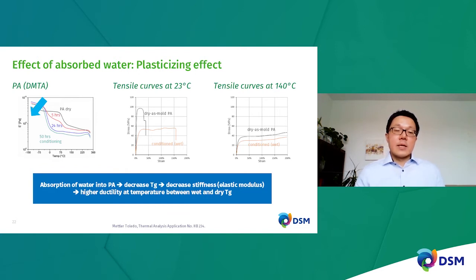To summarize, absorption of water into polyamide typically results in a Tg decrease and a decrease of stiffness, as well as an increase in ductility, because you start to have more and more water in the polymer. This phenomenon also happens for apolar solvents like oil and other types of media that usually exist in the automotive environment. So it is something you need to be aware of.